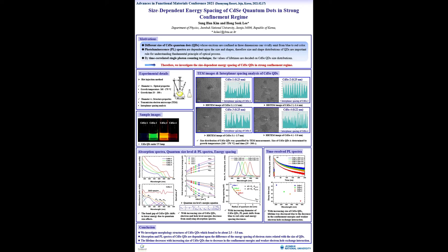We analyzed structure properties by high-resolution TEM measurement. First, as structure properties, TEM images show quantum dot sizes ranging from 2.5 to 5.0 nm. From the lattice fringe of the high-resolution TEM images,